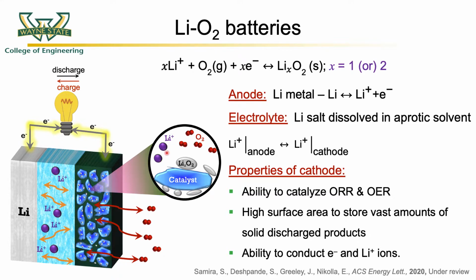At the cathode, gas phase oxygen is reduced by the electrons and the lithium ions, leading to the formation of solid lithium oxygen species. During the charge cycle, these solid lithium oxygen species are oxidized, leading to the evolution of oxygen and redeposition of the lithium back at the other electrode.